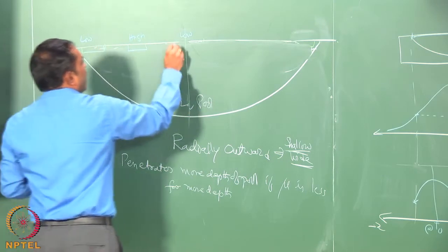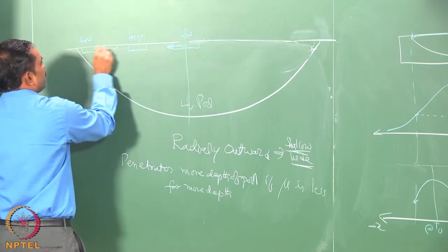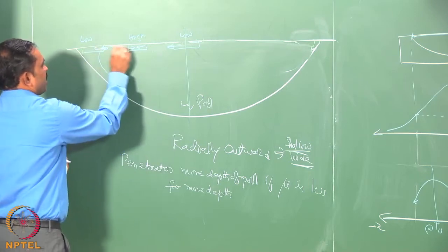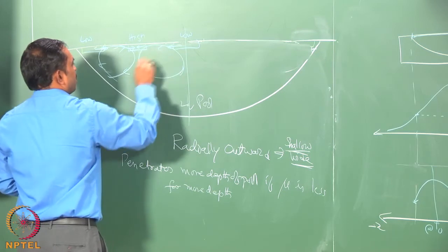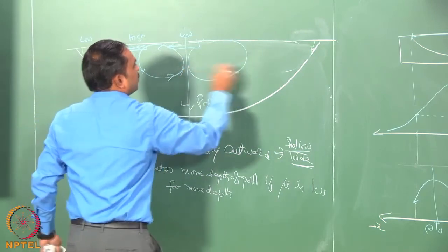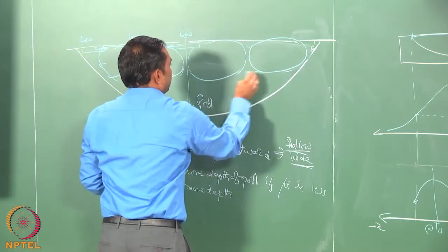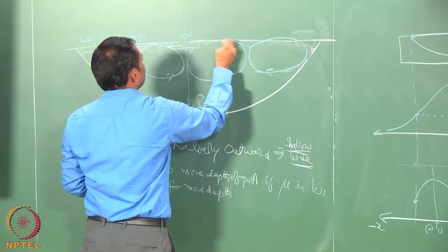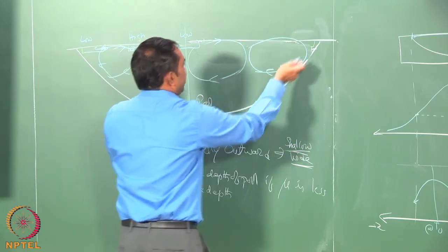So, you have a situation where this wants to expand, this also wants to expand, and here it wants to contract. In other words, you now see that you have two loops, and if you rotate it around, you have flow radially away and radially inward.